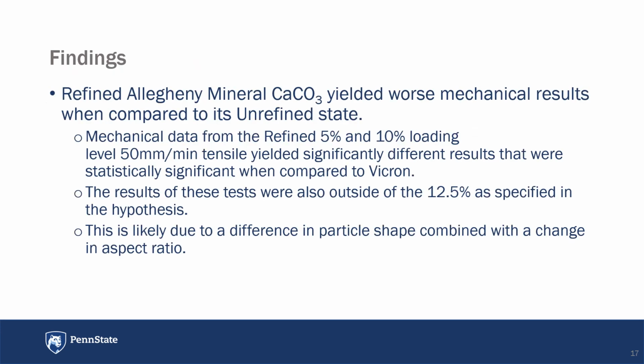Overall, our findings indicate that refined Allegheny mineral material underperforms mechanically compared to its unrefined counterpart, particularly at the 5 and 10% loading levels during the 50 mm per minute tensile testing. These results deviate significantly from Vicron and exceed the hypothesized 12.5% variance. The alterations in particle size and aspect ratio are likely due to the refining process and likely contributes to this discrepancy.